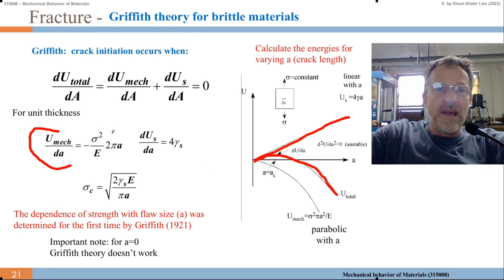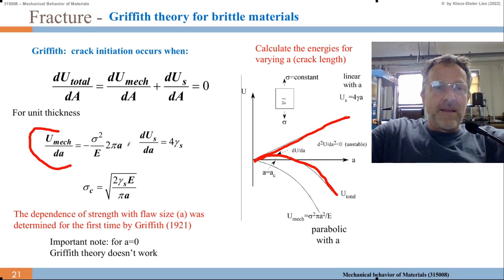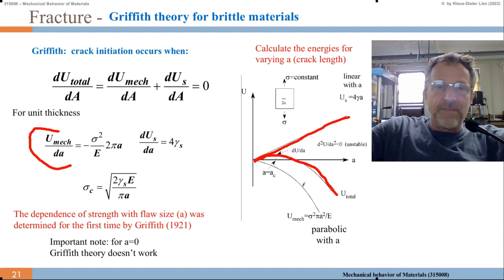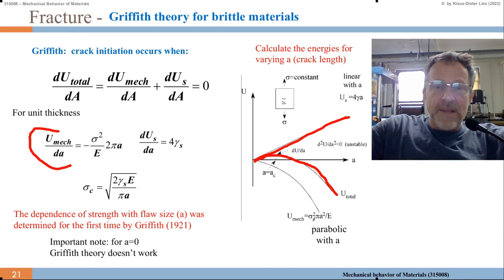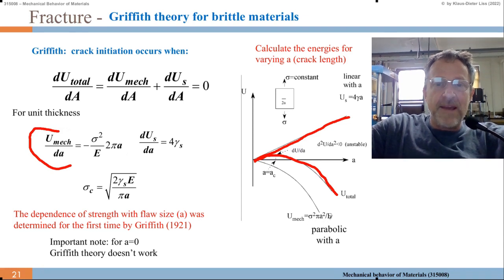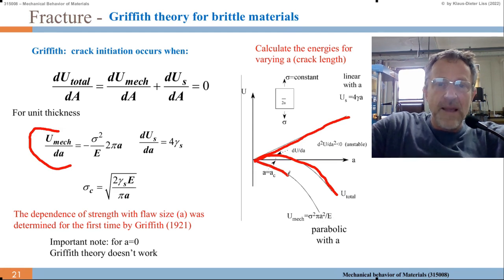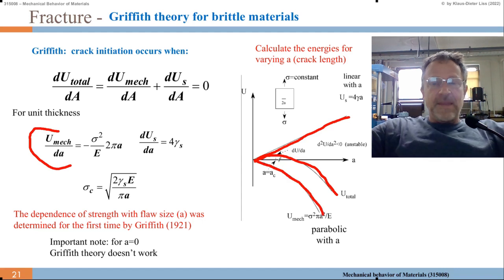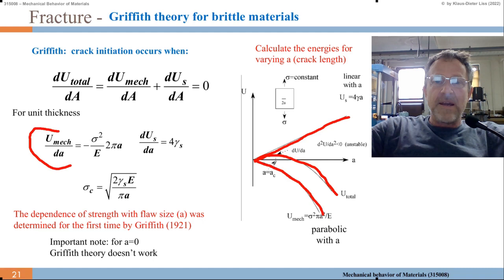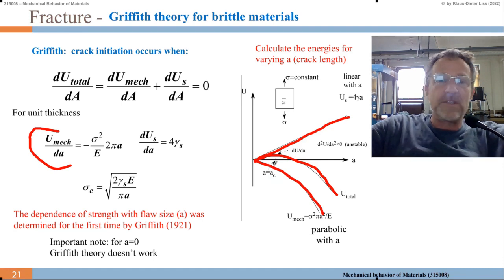The mechanical energy, which is sigma squared pi A squared over E, and negative, we have the minus sign, goes down. That means I open the crack, I reduce mechanical energy because part of the stressed material relaxes. So it goes down in this parabola shape.